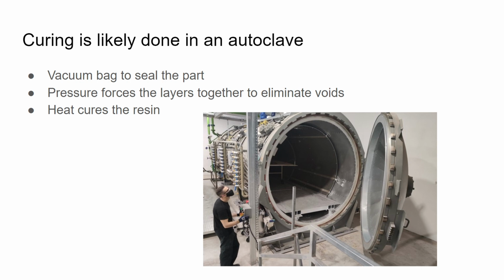Eliminating the voids is key for providing strength and stability to the limbs. They are designed for tens of thousands of shot cycles, which means they need to be very stable and not have any cracks that may form or grow, or voids that may grow in the part. Within the autoclave, the heat would then cure the resin and produce the final part.